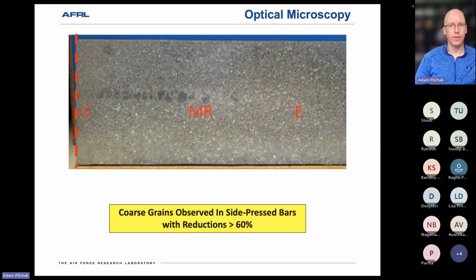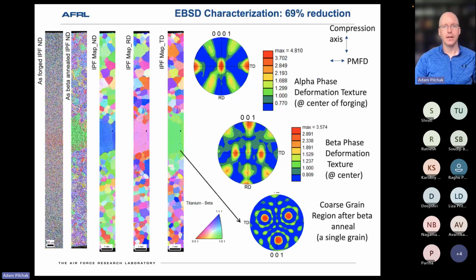Here's an example of one of those side press bars, where you can see right along the center line you get pretty extensive abnormal grain growth. It persists for some distance within the bar, and then it essentially shuts off. That in itself was pretty interesting, and it drove some of the selection of the locations we chose to do point tracking on. We used EBSD, and you've seen a bunch of these already, just to check that yes, we are seeing nominally a single grain orientation within there.